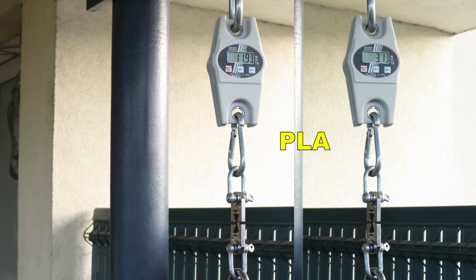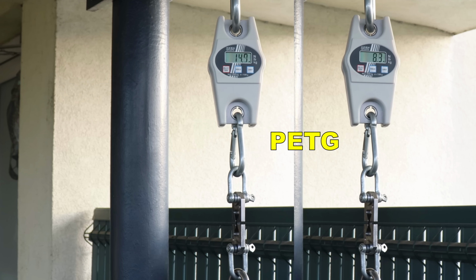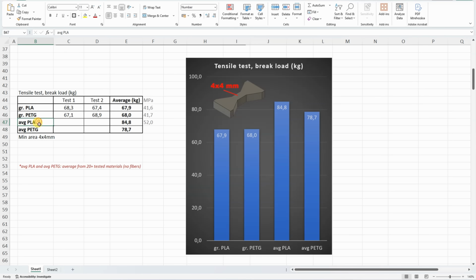The tensile test with horizontally printed test objects. Smallest cross-section area is 4 by 4 millimeters. As I mentioned, I will include here the values for the average PLA and PETG. This is calculated from more than 20 tested materials, and we can see in both cases the graphene-reinforced filaments were weaker, and compared to each other, the tensile strength is very similar.